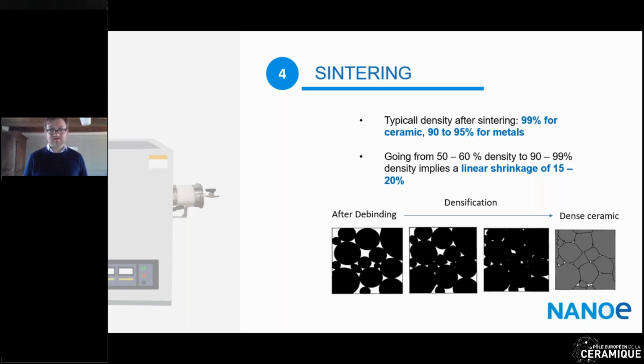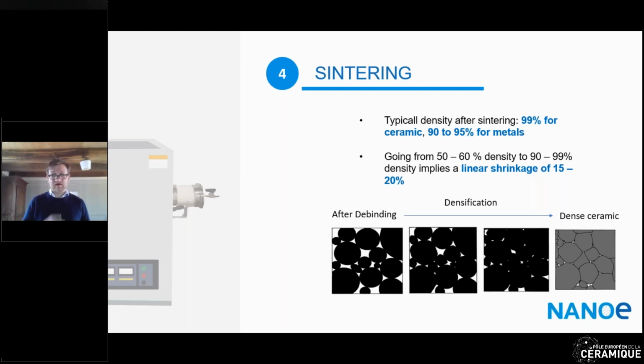What happens during sintering is the porosity that you can see between the grains is going to be removed outside of the ceramic by solid diffusion phenomena, and the grains themselves will kind of melt together and grow to get to a dense microstructure. The typical densities we can reach with this process is up to 99% for ceramic. For metal, it's a bit lower, it's usually 90 to 95, but this is really quite good enough for most